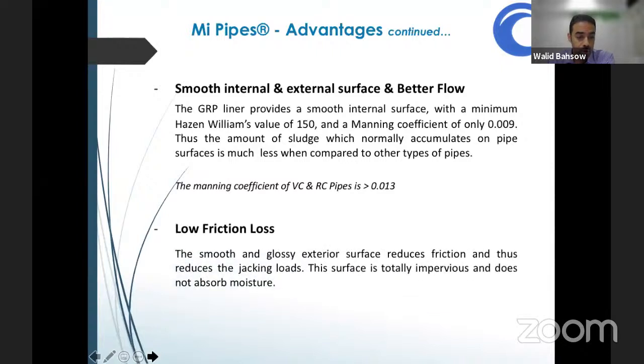For the low friction loss, the smooth and glossy exterior surface of our pipes, because we also have an external GRP liner, which is very smooth and glossy, this reduces the friction and thus reduces the jacking loads required during the installation process. This surface is also totally impervious and does not absorb moisture, and thus the pipe weight remains the same from beginning to end of the installation.